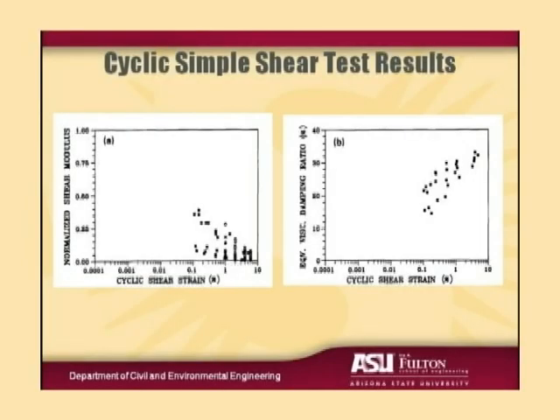The lowest resolution we could get in this cyclic simple shear was about 0.1% shear strain. Typically, when you plot this stuff for earthquake engineering, you want to go down to 0.001% shear strain. So the testing gave us the high strain properties of the material. On the left-hand side, we're plotting the normalized shear modulus: the shear modulus we measured in a test divided by the maximum shear modulus, the small strain modulus. On the right-hand side, we're plotting the damping ratio.